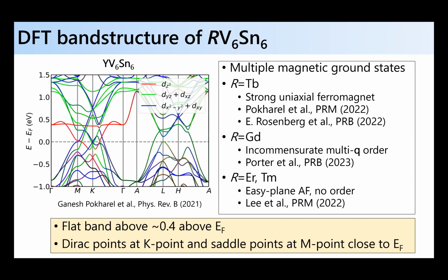This is what the band structure looks like for a non-magnetic variant, so yttrium vanadium 6 tin 6. If you look here at the M point, again, you see there's a series of these Van Hove points coming from the vanadium ions. You can see that there are Dirac points now at the Fermi level, and there's a flat band feature up here, far away from the Fermi level. But one key difference is you don't have this electron-like pocket coming from antimony or tin, like in the 135 system. So it's a little bit different. But in terms of the kagome physics, these Van Hove points are very close to EF.